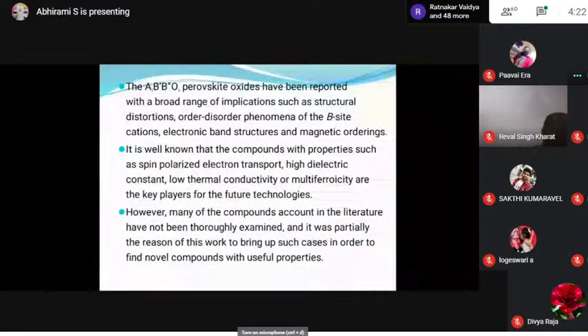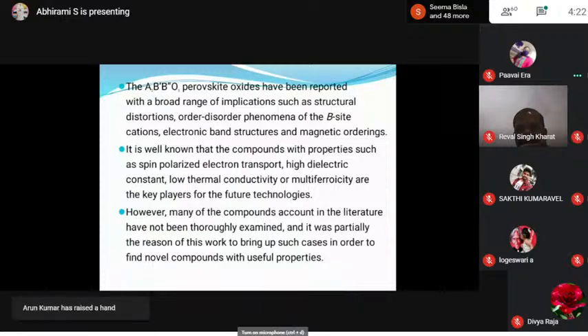The double perovskite structures A2BB'O6 have been reported with a broad range of implications such as structural distortions, order-disorder phenomena of the B-site cations, electronic band structure and magnetic ordering. It is well known that compounds with properties such as spin-polarized electronic transport, high dielectric constant, low thermal conductivity or multiferroicity are key players for future technologies.